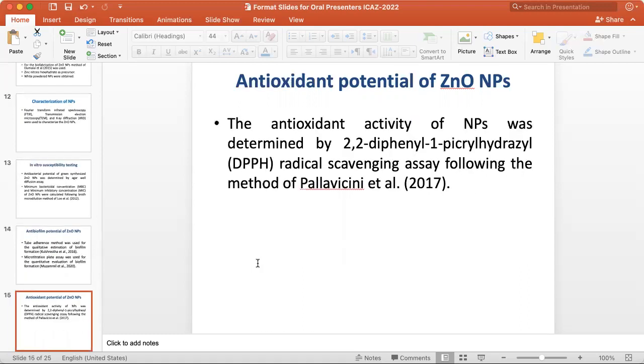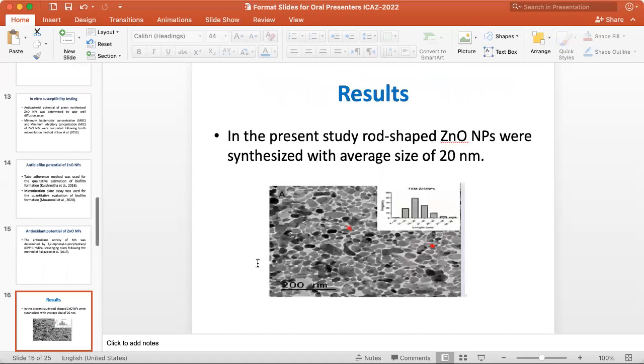At the end, the antioxidant potential of the nanoparticles was also tested by using DPPH radical scavenging assay, in which nanoparticles were used at different concentrations, and the standard was ascorbic acid. It was also used to check their antioxidant potential.